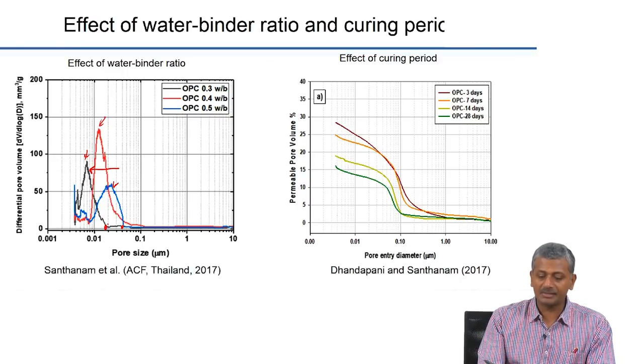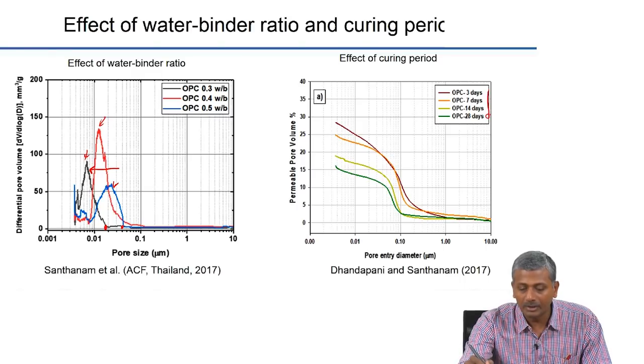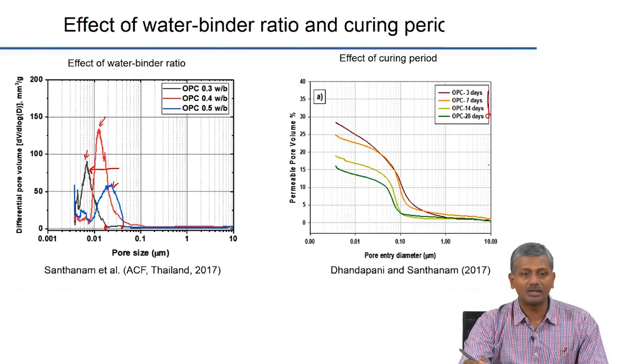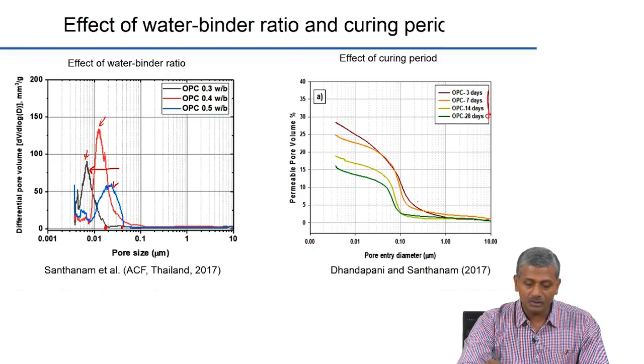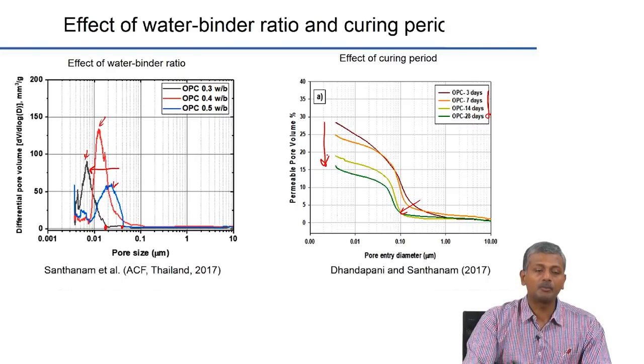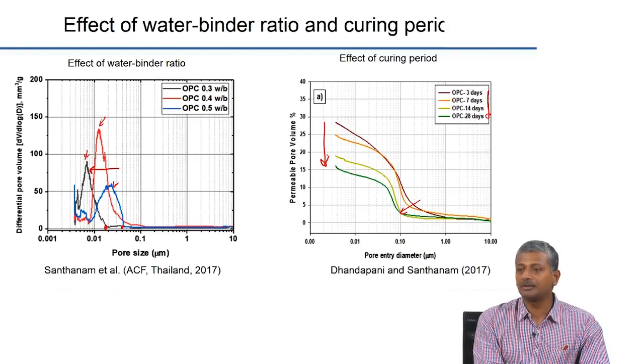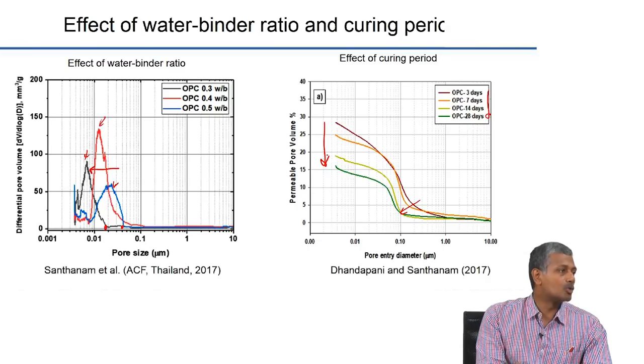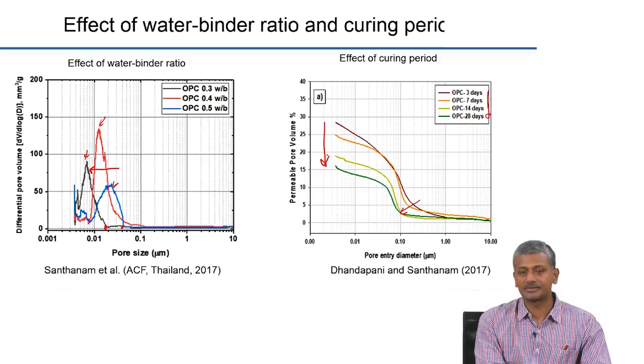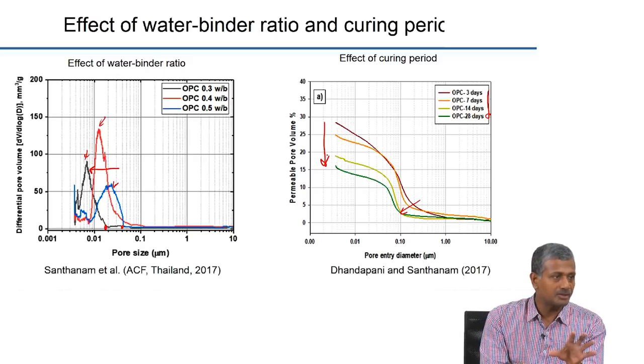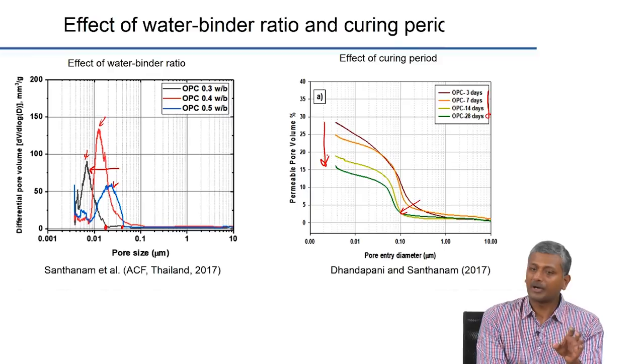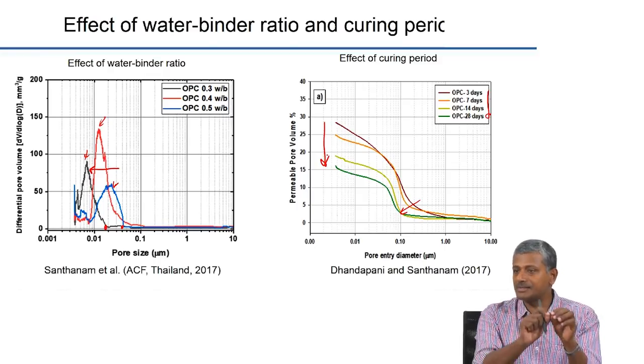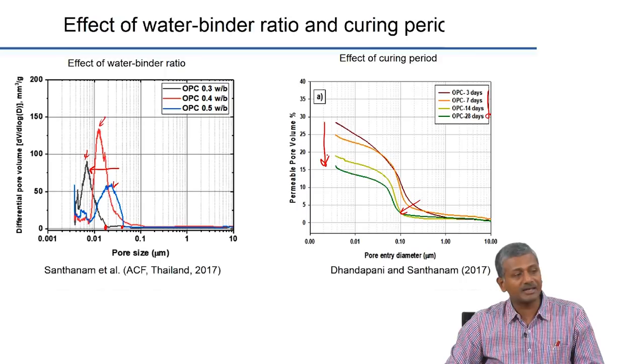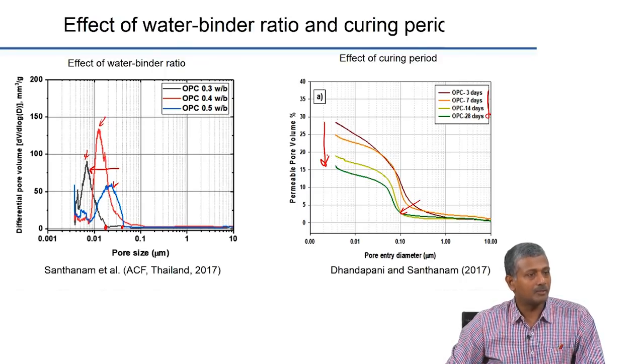What you see on the right is the effect of the age of curing. So curing 3 days, 7 days and 14 days and 28 days, you see that the curve is gradually shifting to the left. You also see a reduction in the permeable pore volume as more and more curing is being done. That is only expected because there is more hydration happening. As more hydration happens, there will be lesser porosity and permeability in the system. Okay, so what you are measuring here is the accessible porosity. Apart from that, there may be also porosity that is discrete from each other, not connected. So that is inaccessible porosity, but that you are not seeing in your MIP results.